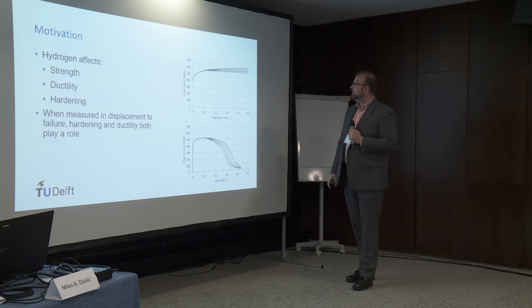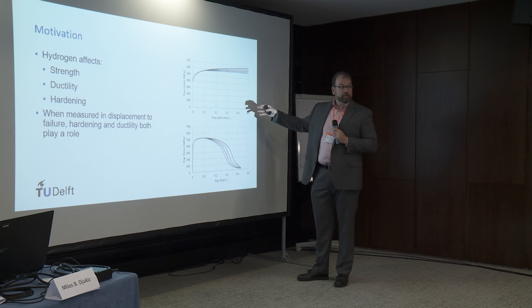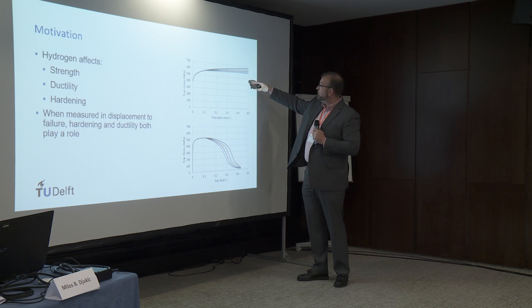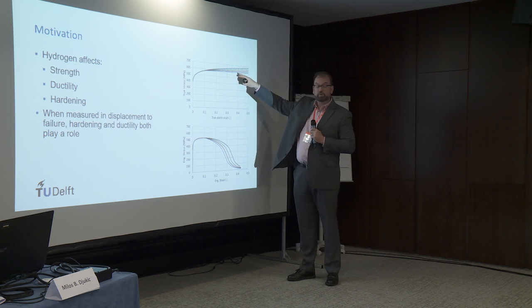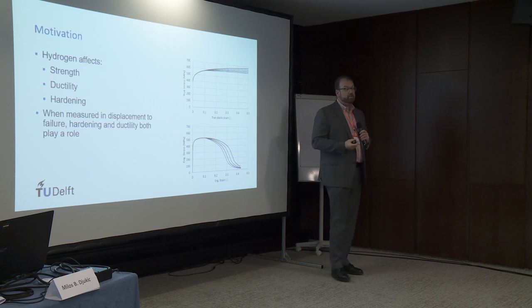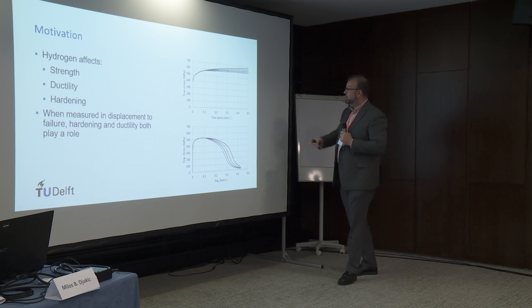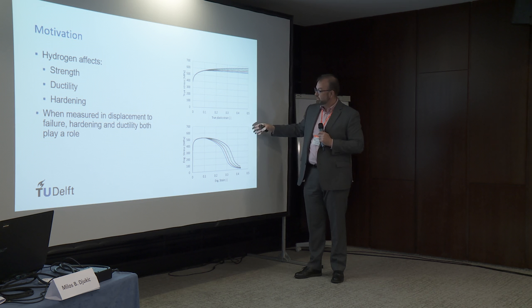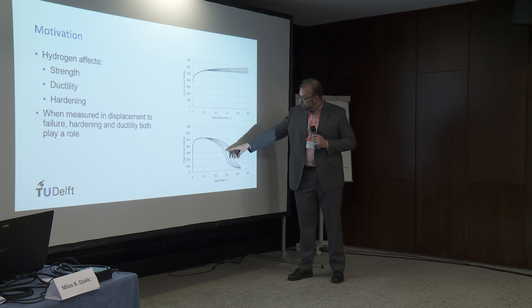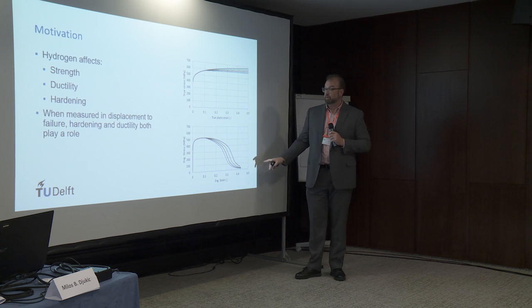To demonstrate that, I asked Mr. Asghari to perform a simulation of a tensile test with a number of different material models. Frankly, these material models aren't all that different, and none of them actually soften. The lowest one is perfectly plastic at some point, and then we have various different levels of hardening. Notably, there is no damage in this model — no softening, no damage, no fracture strain. And yet, when we run the simulation of the tension test, we get engineering stress-strain curves that look like this, and evidently, various different ductilities.